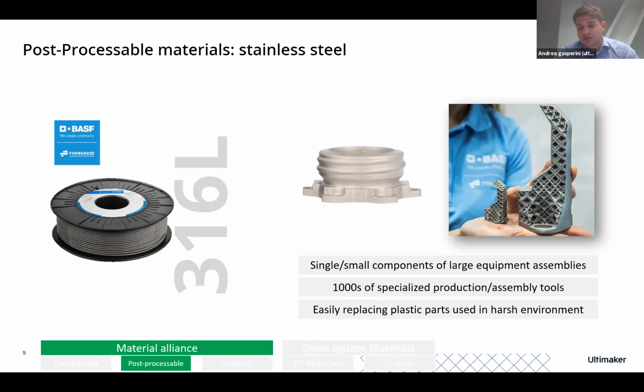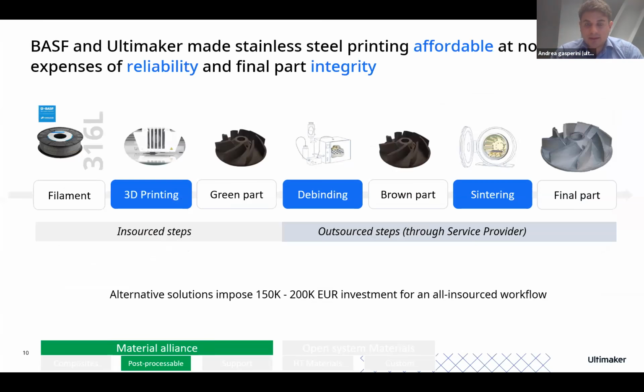The benefit of this technology in a nutshell is decreasing the cost of production for metal parts and producing lightweight structures in metal. Because using an extrusion technology, you can have an infill inside and reduce the weight of the metal part versus a full density part. You also get faster design iteration for your metal parts. But as you might know, not all parts that you produce with the 316L are ready to be used. You need 2 extra steps along the line, the debinding and sintering steps, in order to have the final part.